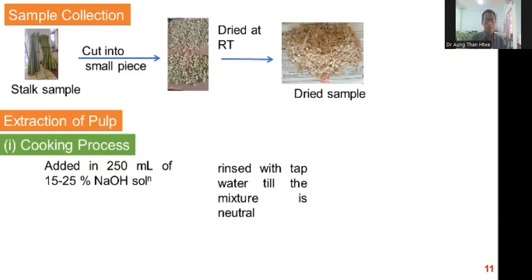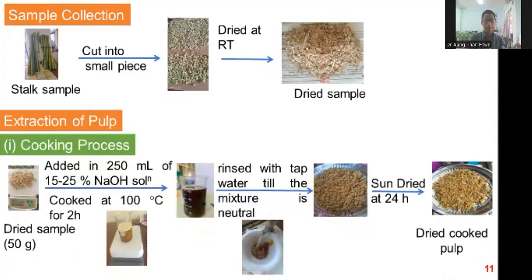The first one is the cooking process. The dried sample, 50 grams, was treated with sodium hydroxide solution at 100 degrees Celsius for 2 hours. Then it was rinsed with water until the pH was neutral, and sun dried for 24 hours to obtain fine fiber.